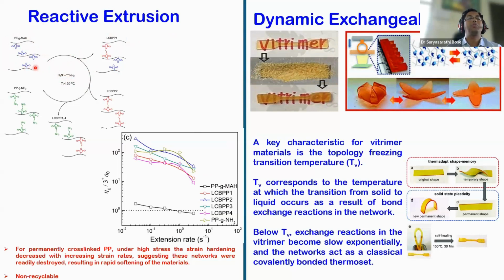But when they bond, this particular chemical bond is a permanent bond, and you can only break them at higher temperature, but you cannot cut them and rejoin them. So this is the difference between reactive extrusion and dynamic bonds. In the case of dynamic bonds, you can break them, but they again join, which gives us a sense that they can be self-healed, they can have a shape memory effect, and so on, which also means that the vitrimers can be reground and can be made again into the same product without loss in the property.